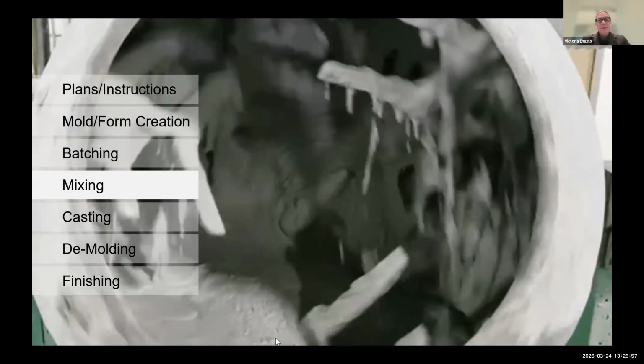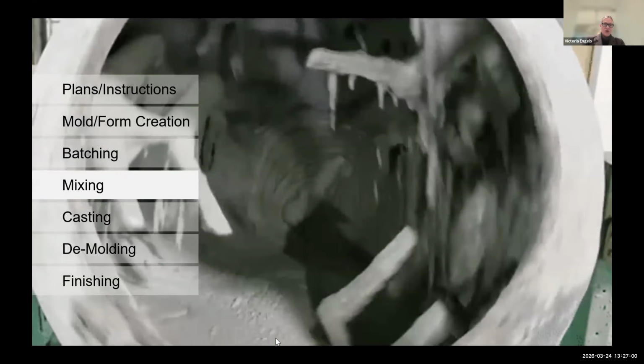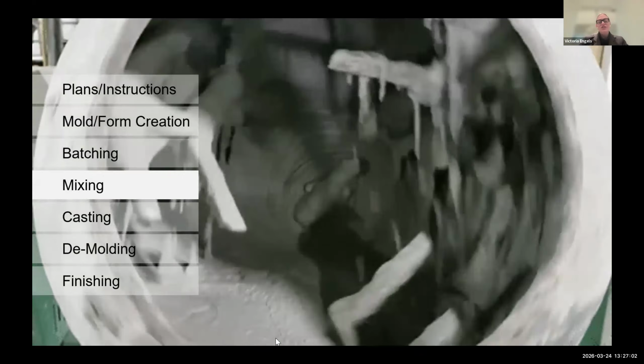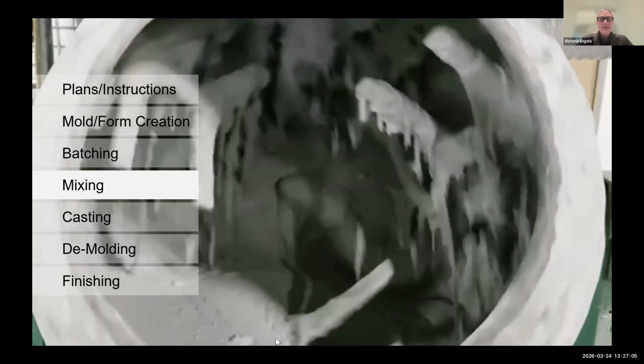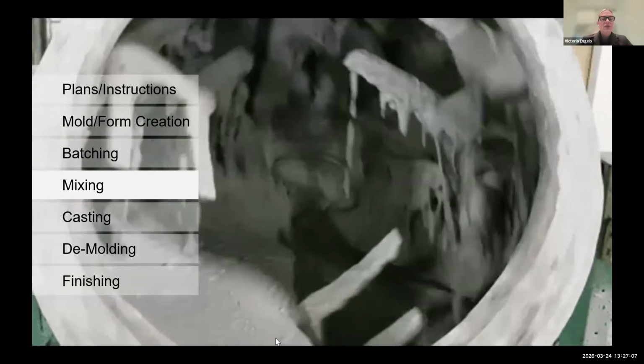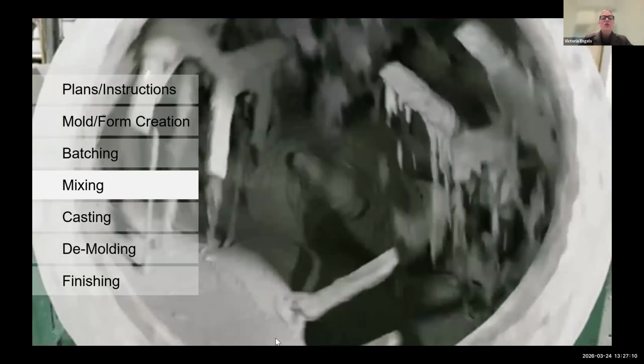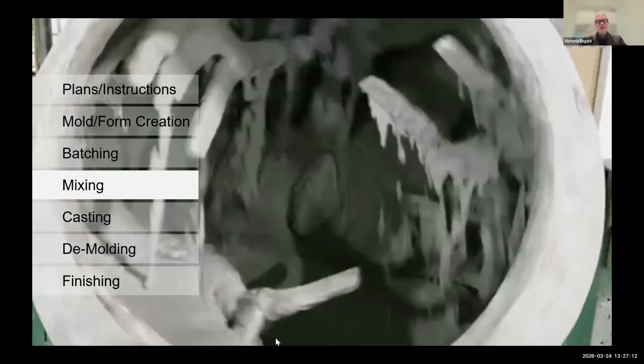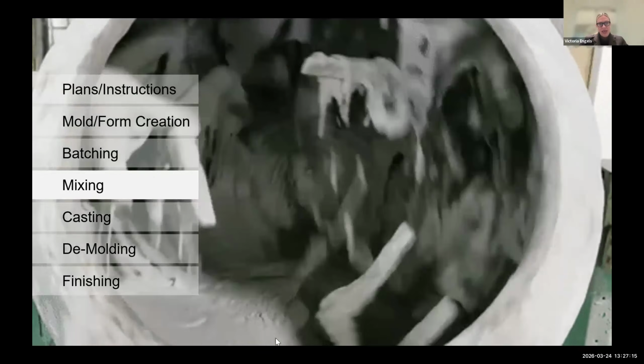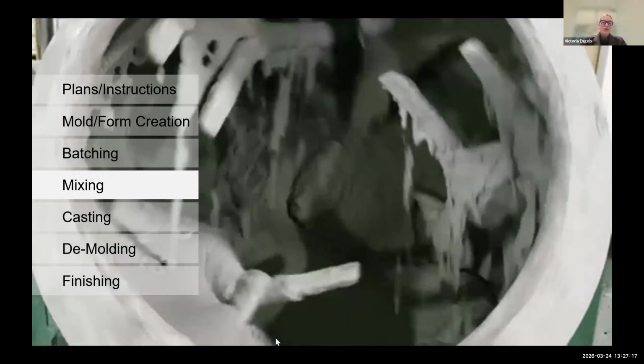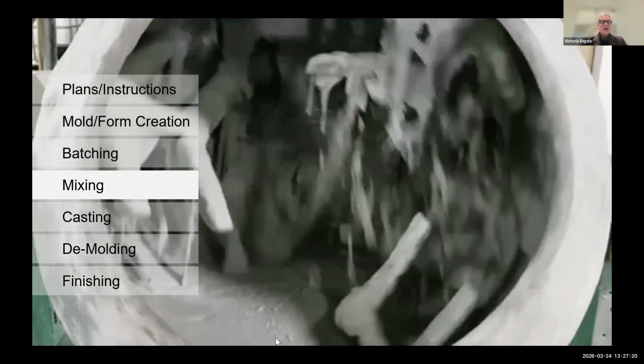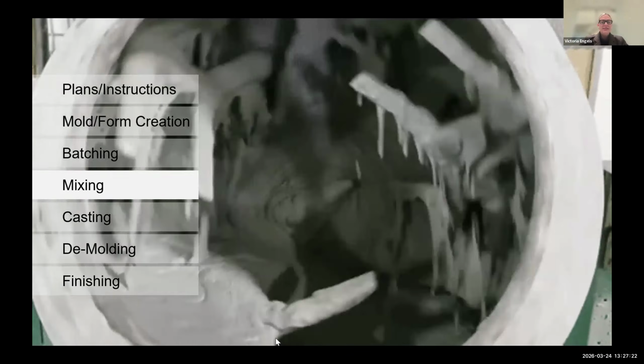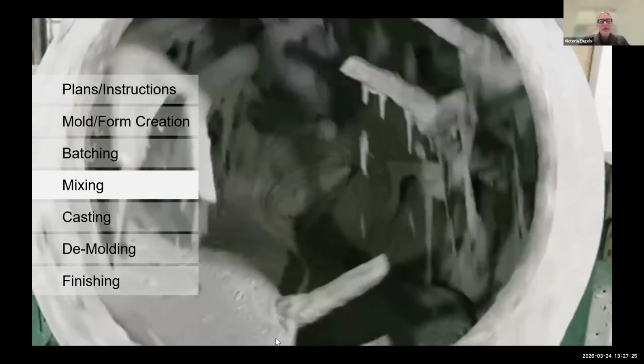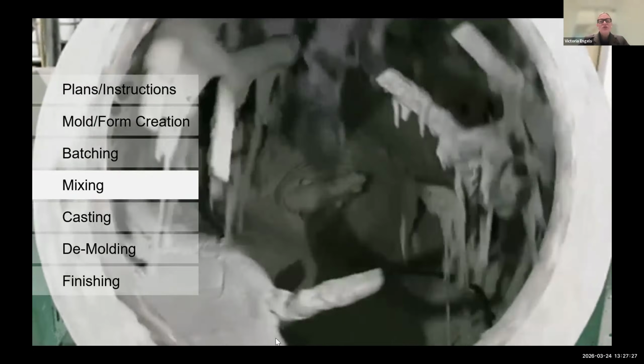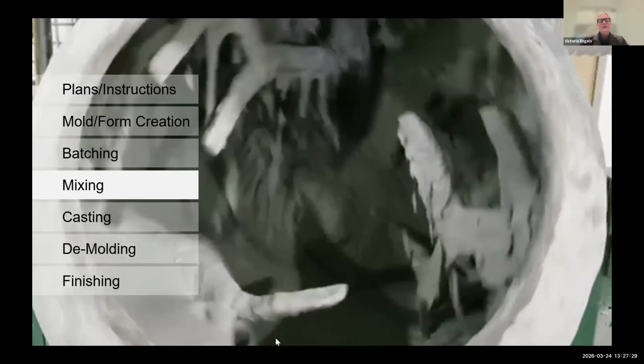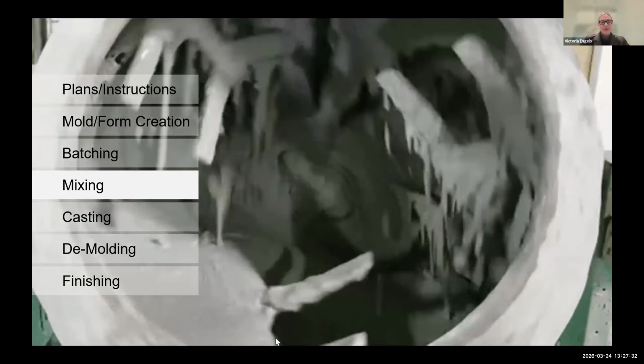The batched ingredients are then methodically loaded into different types of concrete mixers, and depending on the type of project that's being cast, the temperature, timing, ingredients, and the order of loading these ingredients all create variables and can create challenges to getting the concrete to behave properly. Plasticizers can be used to reduce the viscosity of the concrete mix to a near water consistency without having to add water. The concrete shown here actually has very little water, but it flows that way due to plasticizers.